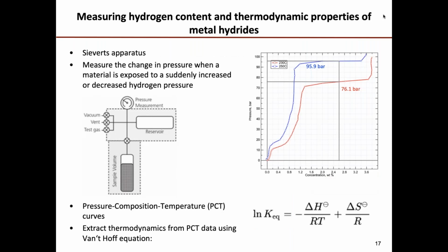Now, one of the most important things we measure is the thermodynamic properties, and we do that using something called a Sievert's apparatus, which is shown schematically on the left there. Basically, what you do is you put a sample of your hydride in there, and you heat it a little bit and desorb some of the hydrogen into a calibrated volume, and you keep doing that, and eventually you get to a point where you reach a plateau, and that's the equilibrium pressure of hydrogen above the material at a specific temperature. And you can do that as a function of temperature, and that gives you data that you feed into something called the Van 't Hoff equation, shown down there in the lower right, and from that data, you can extract both the enthalpy and the entropy. So knowing those two numbers allows you to predict the pressure of hydrogen above a material as a function of temperature. And that's absolutely a critical engineering number to know.